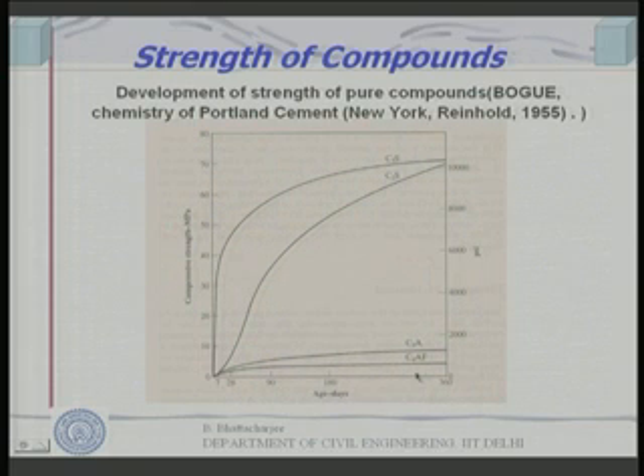Right. Let us see which gives the maximum strength. If we look at it, this is age in days, and this is compressive strength given in megapascal. C3S shows very high early strength, in the initial ages C3S reacts and it has CSH gel which has the bonding property. Basically, when cement reacts with water, it forms this gelatinous structure which has enormous surface area, possibly 1000 times more than that of the cement itself, and the surface forces start dominating. Van der Waals kind of forces, bonds, are established between the material there and this CSH gel. So, CSH gel has a very large surface area, can bond inert material such as stones or sand, and that is how it gives the cementing property.